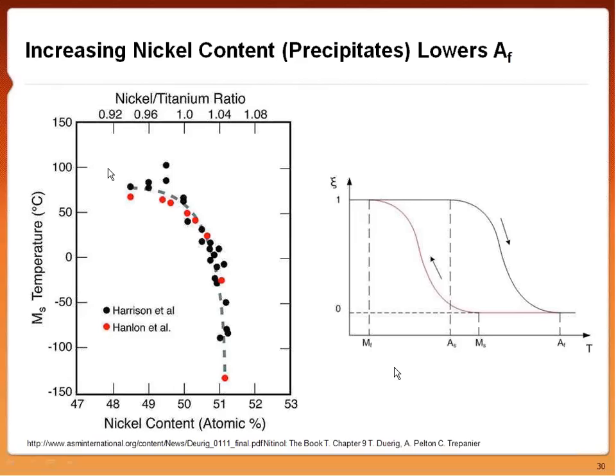So you can see here that if we're on the cooling curve, it means you're going to start to see martensite at higher temperatures. And the same thing will happen with the heating curve. It basically means you're going to start to see austenite at a higher temperature as well. So we can use this to our advantage in changing the slight material properties to give us better stiffness, better performance, and better strength in our device.